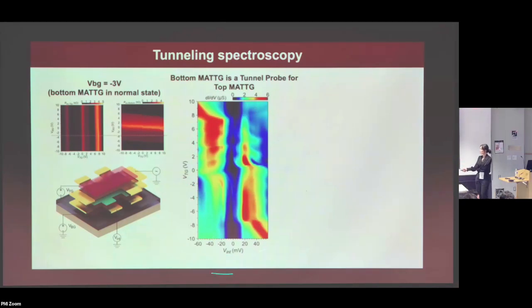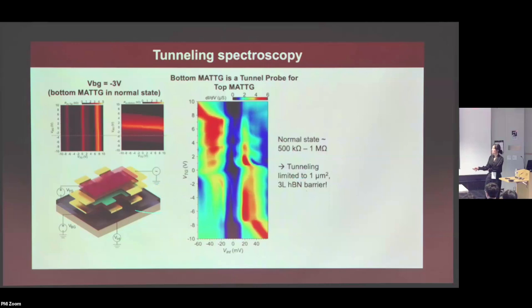And the x-axis is the interlayer tunneling voltage, which is basically the energy scale that you can probe. So it's a very large scale map. The first thing you can realize is the normal state resistance is around the value that you would be expecting for a 3-layer hBN tunnel barrier for the region of that little hole that we drilled. So this confirms that our tunneling is happening in the middle of that core device region where we're also measuring the transport, and not some random other regions. So that's a sanity check that we can do.